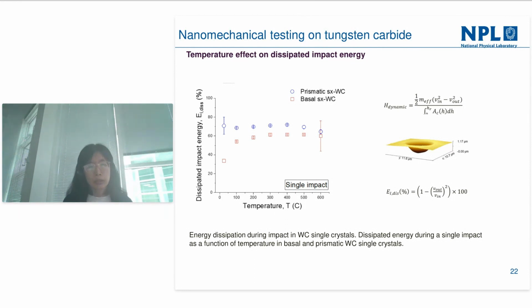So this is consistent with our observation for the quasi-static test up to high temperature, an indication of plastic deformation along certain planes, with more dislocation systems triggered with increasing temperature.